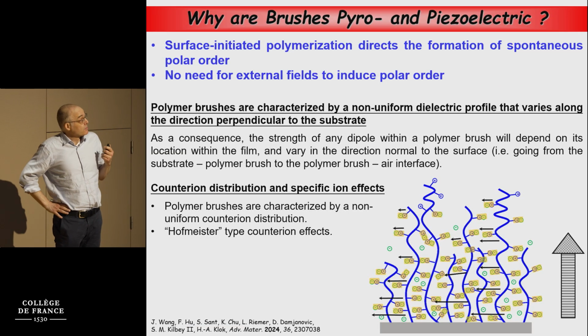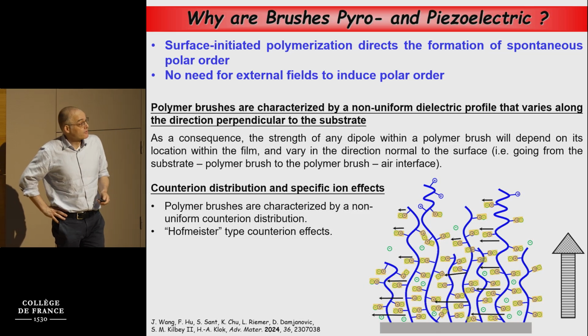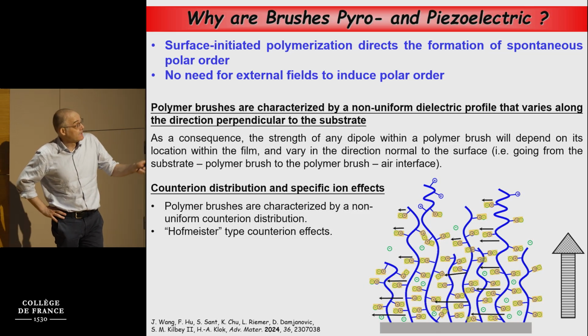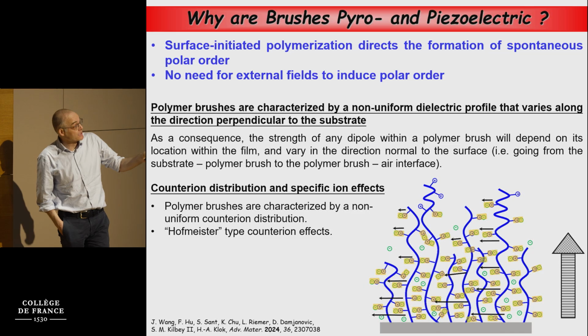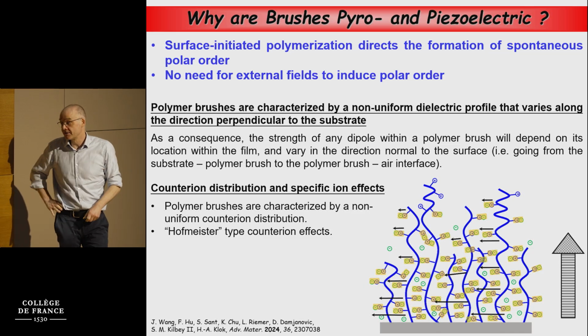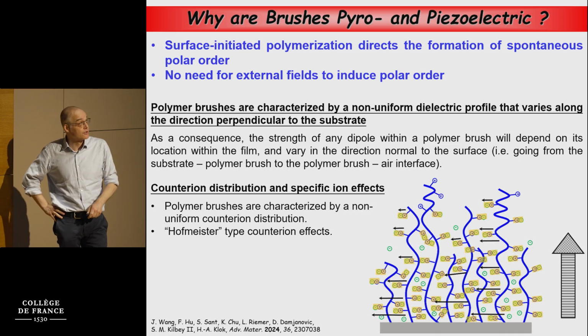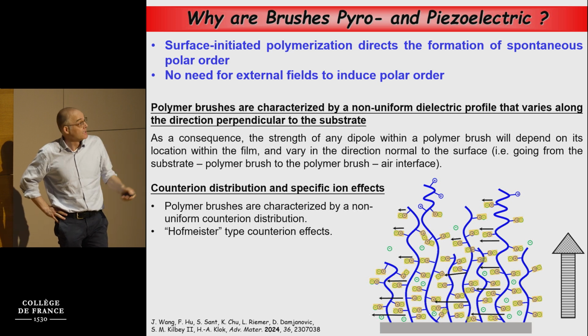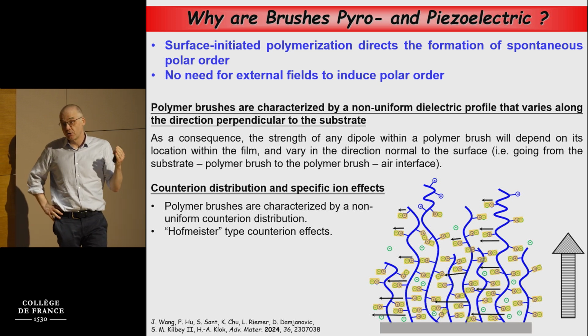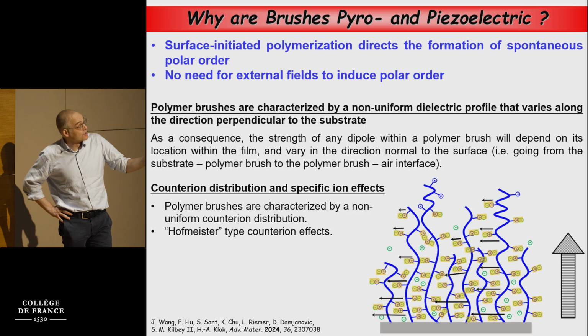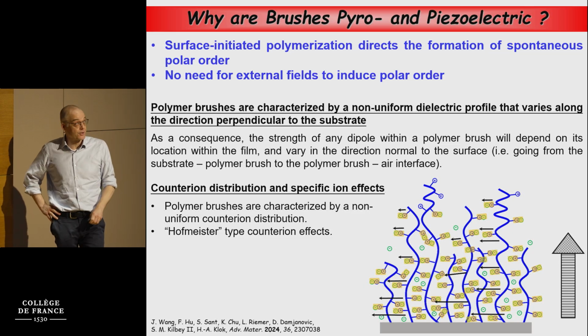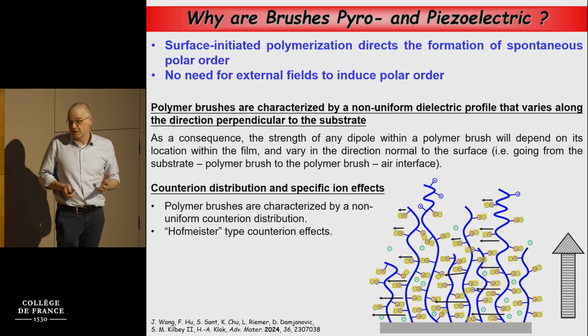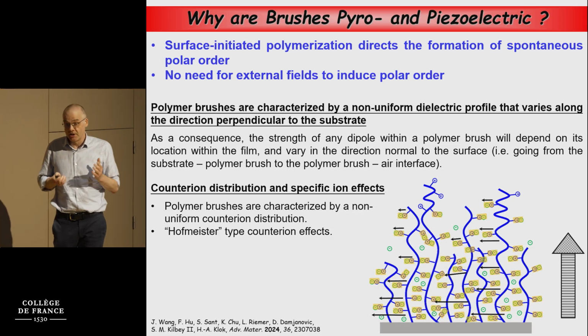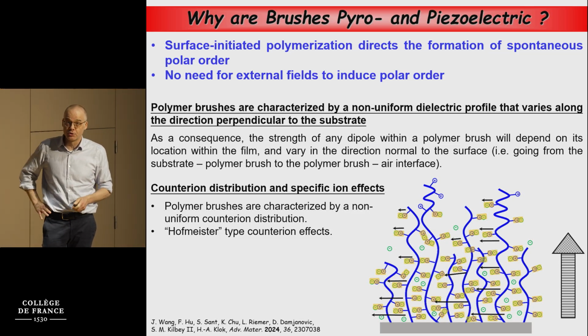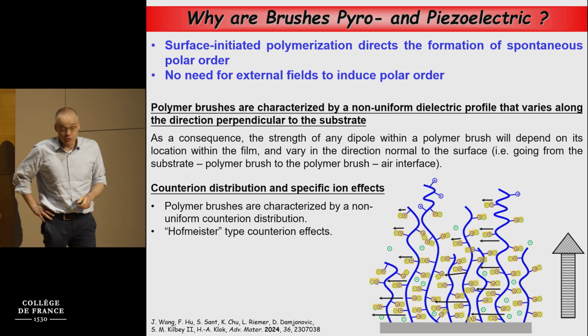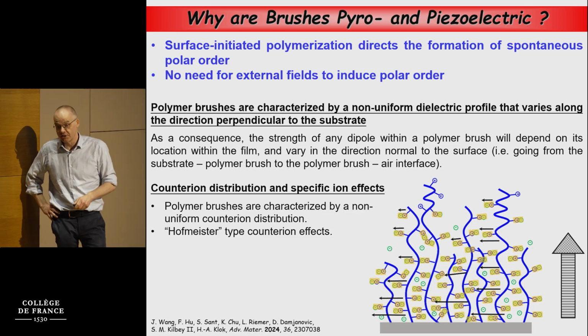So the conclusions from this are fairly obvious, I would say. I think this clearly shows that surface-initiated polymerization somehow allows us to direct or induce a spontaneous polar order in these films, polar order of some sort. And this generates pyro and piezoelectric responses without the need for external fields to induce polar order, which I think is quite interesting. The big question for these systems, however, since they are polyelectrolytes, and polyelectrolytes are non-trivial polymers, I would argue, is to try to rationalize why these materials show this behavior.